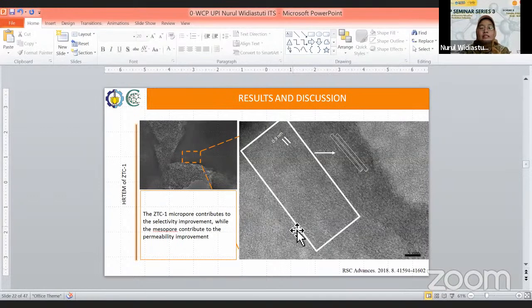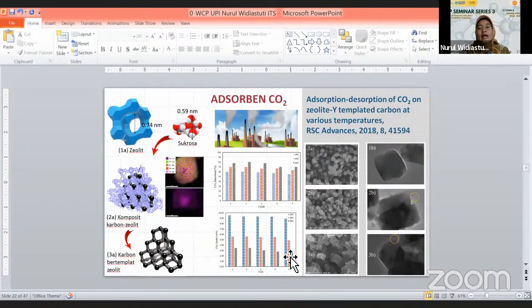And this is the result from the TEM analysis, which shows the micropores, and we can also find mesopores in the material. So the benefit of these pore structures is that the micropores will contribute to the selectivity improvement, while the mesopores will contribute to the permeability improvement.